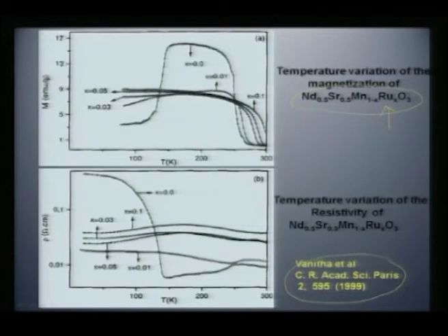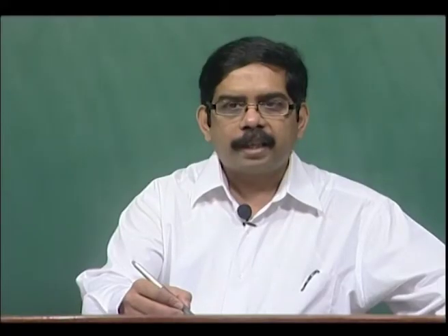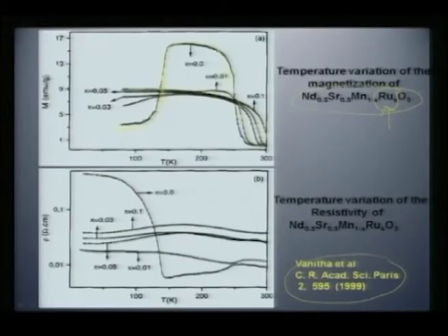What is interesting here is the moment you start putting just 1% of ruthenium in this charge ordered manganate, immediately this charge ordering is removed and the system becomes a ferromagnetic metal. And as you substitute more and more ruthenium, the system is becoming more ferromagnetic, and therefore, from a charge ordered or an antiferromagnetic state you can make it a ferromagnet by simply substituting with ruthenium.